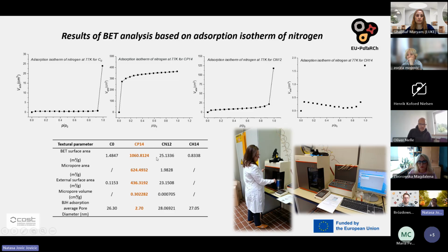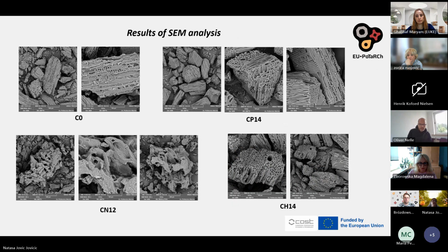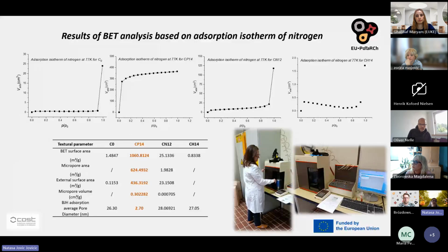A somewhat higher surface area we found in the sample activated with sodium hydroxide, about 25 square meters per gram. Regarding micropore volume, it is the highest for the sample activated with phosphoric acid, confirming its strong microporous character. Average pore diameters are also provided, showing that the CP sample has much smaller pores compared to other samples. So these results demonstrate that the activation process applied with phosphoric acid greatly enhanced the surface area and microporosity, making it the most promising material in the adsorption study.